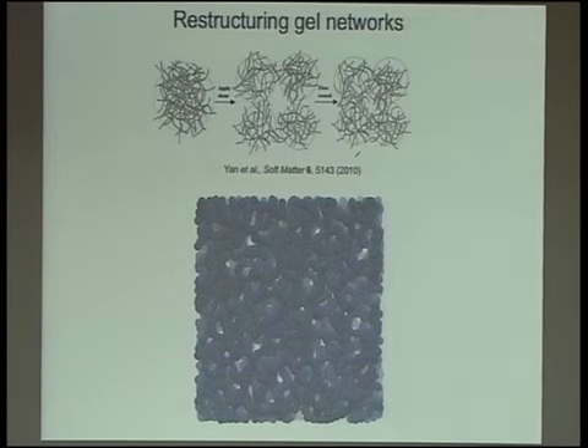And if one wants to push it further, an interesting thing is that you can now think of designing, for example, a gel network, where under deformation you break up part of the gel, but in fact, as you proceed shearing the system, you also bring part of the structure together. And so if you were able to properly design this feature, you could design a system in which you break the structure so the system starts to flow, but then the same structure actually self-heals. And so it arrests the flow and so on.